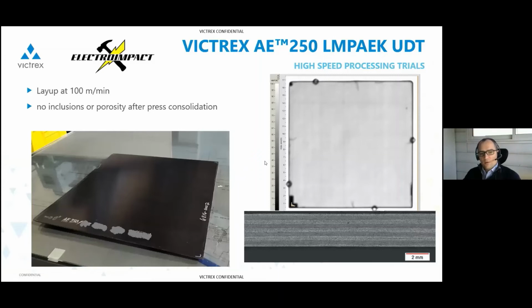But here, the focus was the layup stage, not really optimizing the consolidation phase. We don't believe that would change the result. Anyway, there was no inclusion or porosity in the laminate. And as you can see here on the microcut, we made a C-scan and a microcut, and the result was also pretty positive.